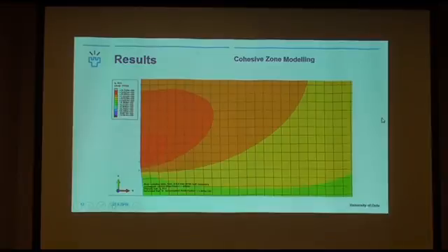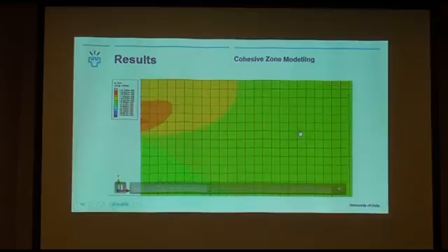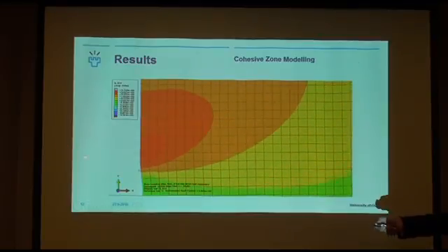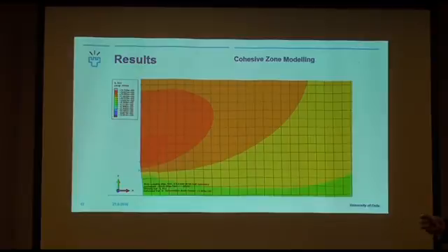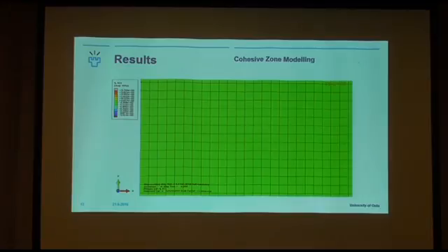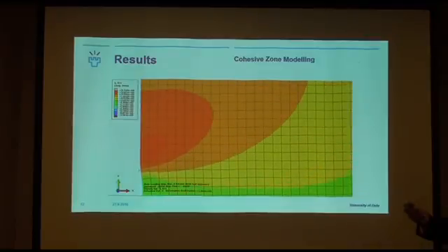Yes, well, slow video which just shows the separated elements. So we took the failure point as the complete separation of the second element in our model, which corresponds to the fracture propagation before the brittle fracture in the specimens.